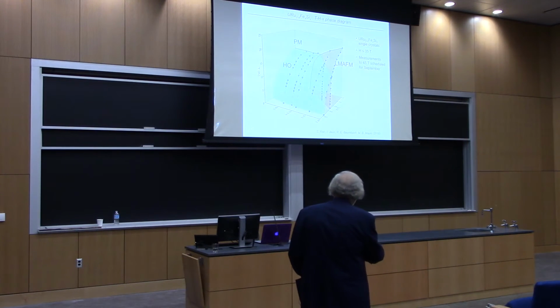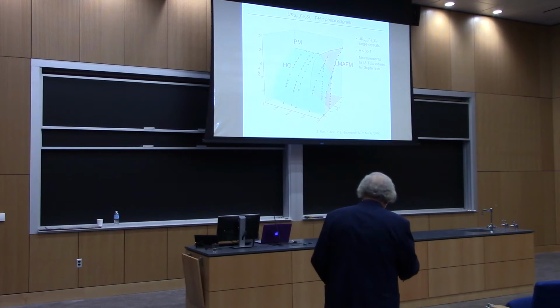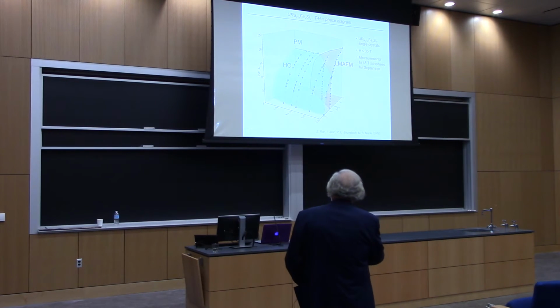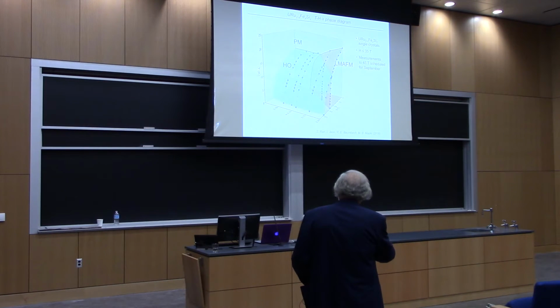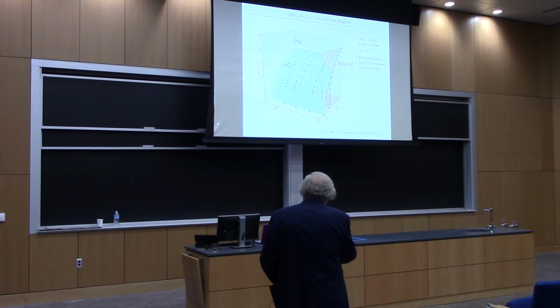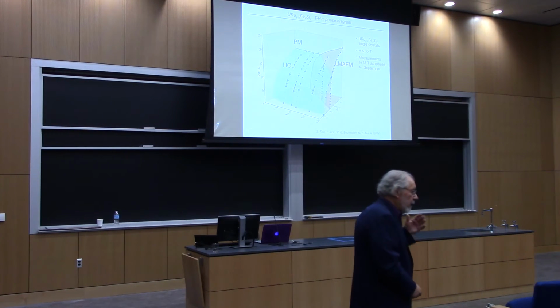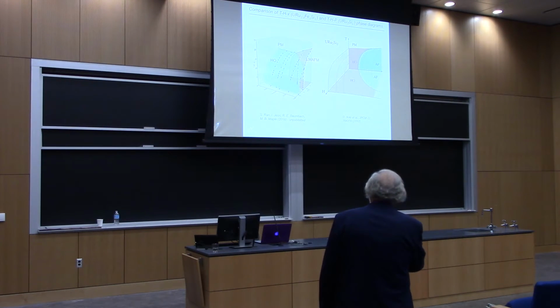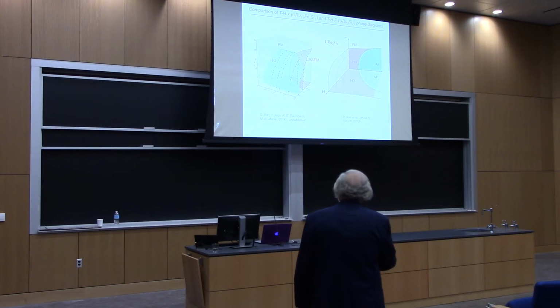So you can then make a three-dimensional plot of the data that we've taken so far. And so here's temperature versus x versus field. And so hidden order is suppressed this way, then you suppress antiferromagnetism, and then go into the hidden order phase and suppress that. And we're especially interested in what happens down here, because that's where you see all these other cascading quantum phases. And this is compared to some work by Aoki on the pure compound under pressure, and this is the schematic phase diagram that he prepared. So this would be pressure, since those are pressure measurements, and they're certainly consistent.